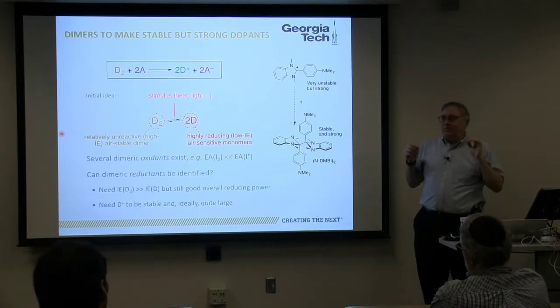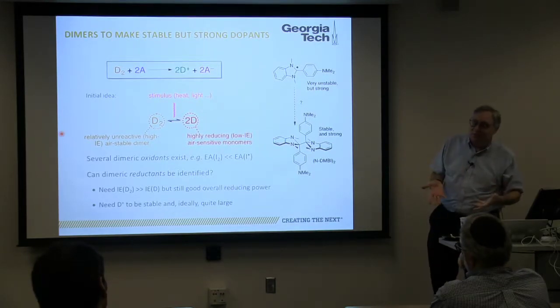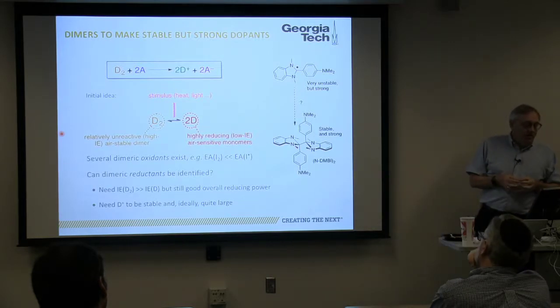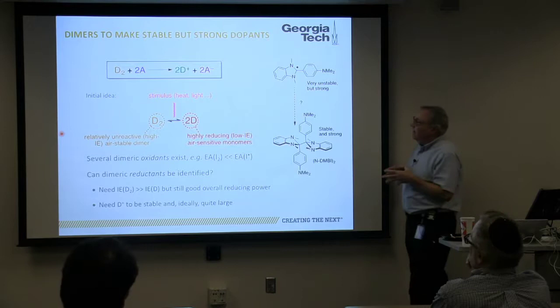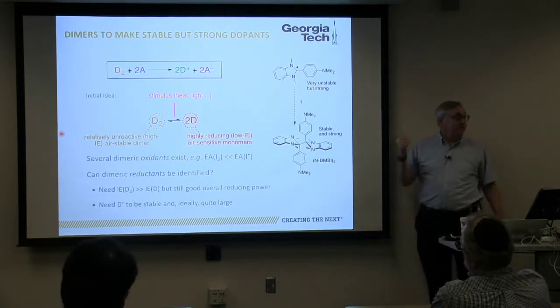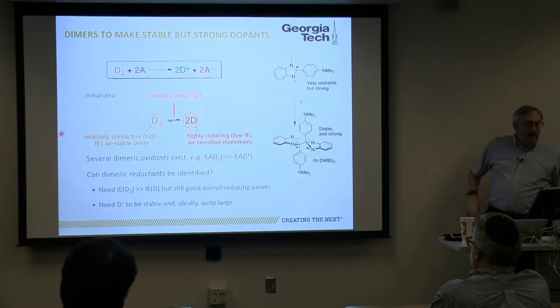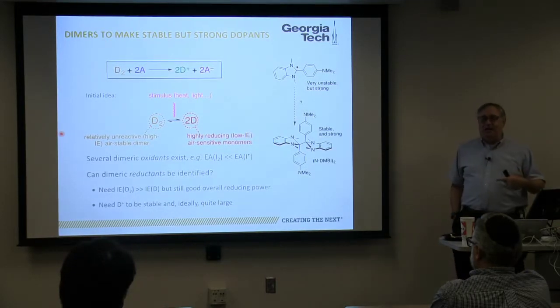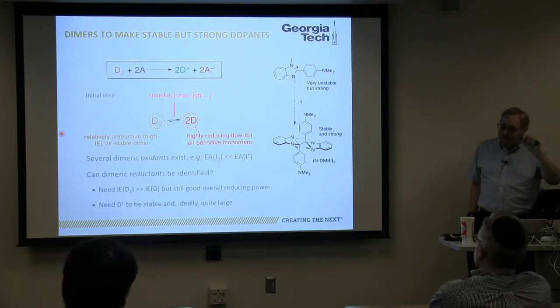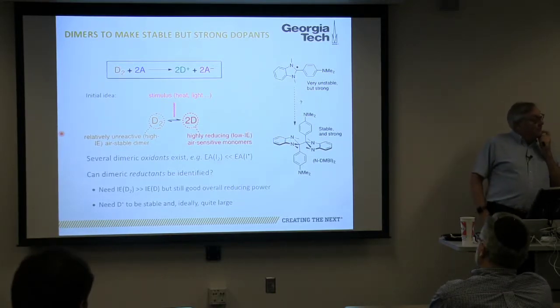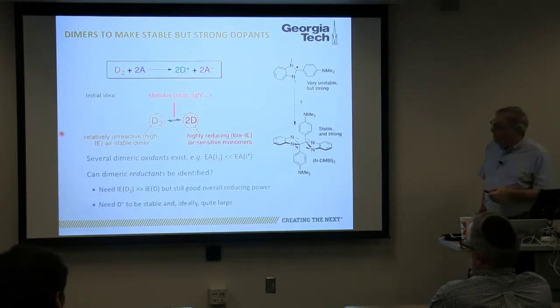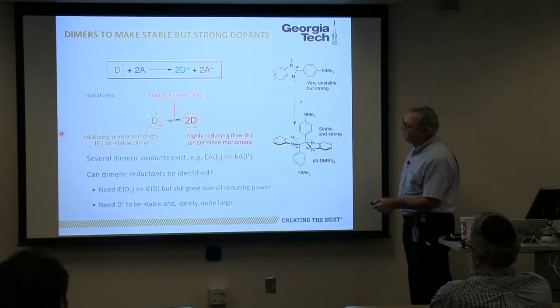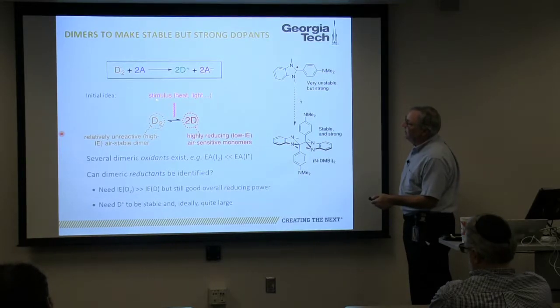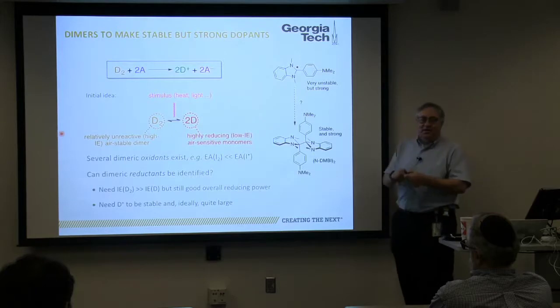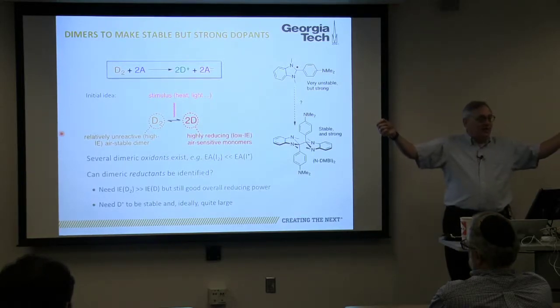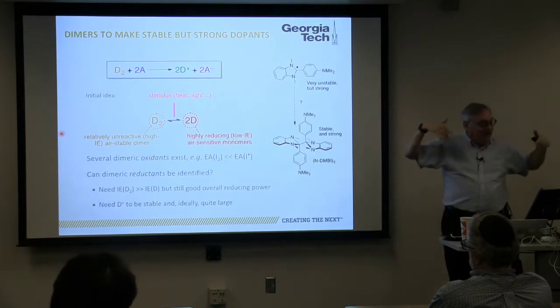But we don't want that bond to be so stable that it loses all the reducing force. Okay? And so then the idea is that we have that dimer. It can react with two of these acceptors to give two cations and two anions. Okay? And so what we are doing is we're kinetically stabilizing the dopant at the cost of also thermodynamically weakening it a bit. But we might be able to make it air stable. Okay? And so our initial idea was to basically have a system where we can take the dimer and using heat or light, we can just cleave the dimer into two things. Just homolytically break the bond and then generate the reactive species, and then it will dope.